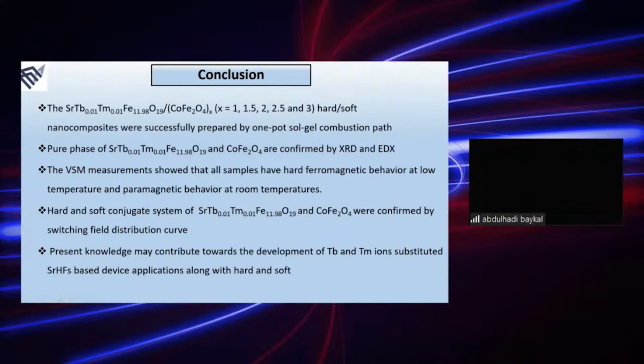Second, the phase purity of all products was confirmed by EDX and XRD. And the VSM measurements show that all samples have hard ferromagnetic behavior at low temperature and paramagnetic behavior at room temperature. Fourth, the hard and soft conjugate system of strontium and cobalt is confirmed by the switching field distribution curves that I showed you before. The present knowledge may contribute towards the development of terbium and thulium substituted strontium hexaferrite based device applications, along with hard-soft microwave absorber materials.